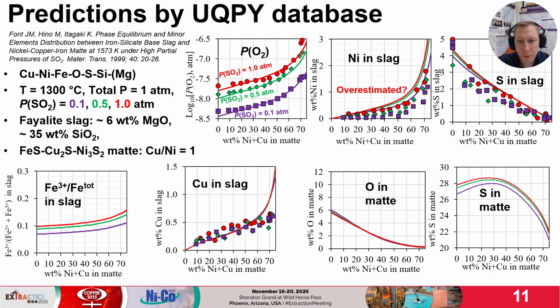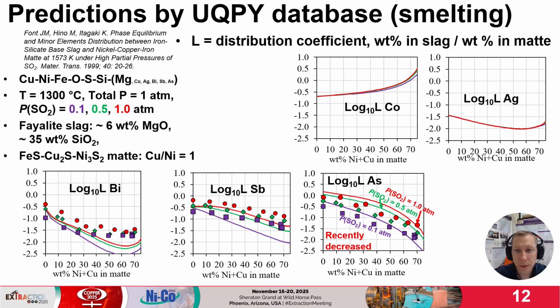We believe there's a fundamental problem in the model for matte starting from the copper-sulfur system, pushing nickel into the slag. But this problem is hard to fix. We already spent significant resources in these directions, but no breakthrough so far. The distribution coefficients for high copper mattes are also described, with some unusual behavior for bismuth. This is something to be addressed either experimentally or using further modeling.